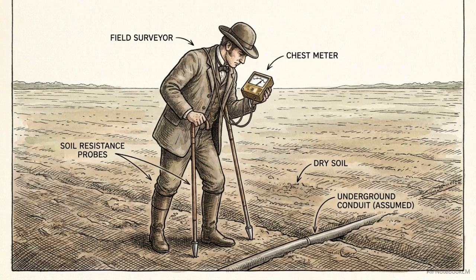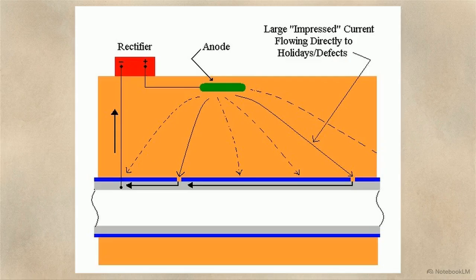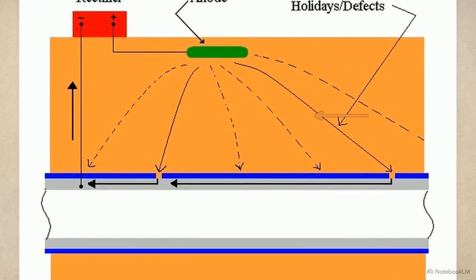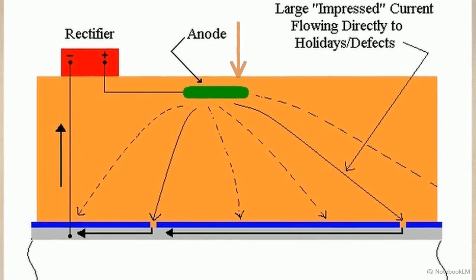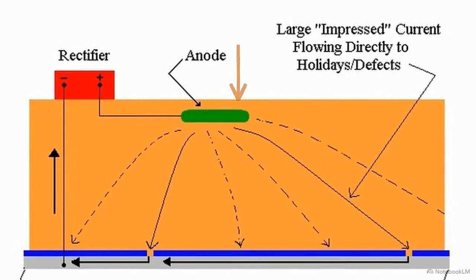Engineers hunt for these anomalies using a direct current voltage gradient, or DCVG, survey, which forms phase 2 of the ECDA process. As ICCP current travels through the soil, it rushes rapidly into a coating defect. This intense draw creates tight, concentric equipotential lines radiating upward through the earth. These lines represent a rapid voltage drop, creating a measurable electrical gradient at the surface.